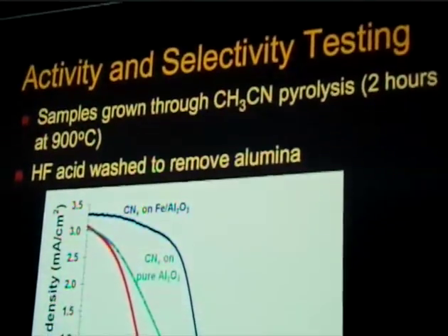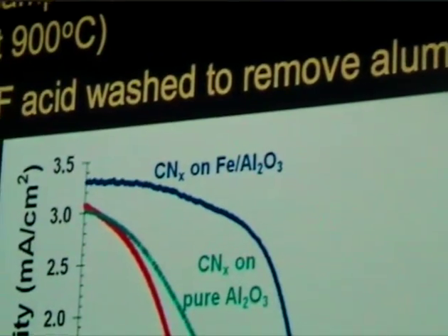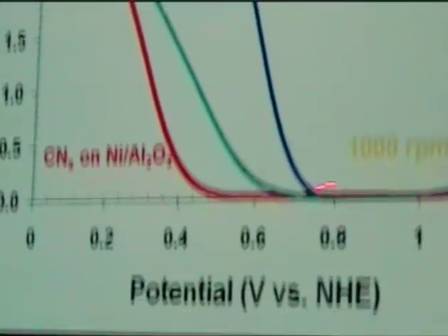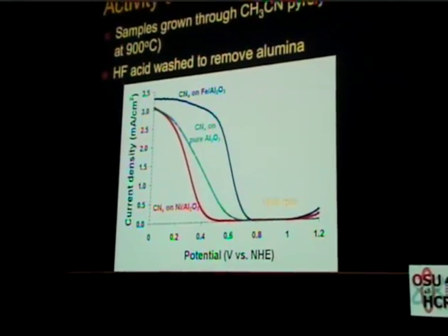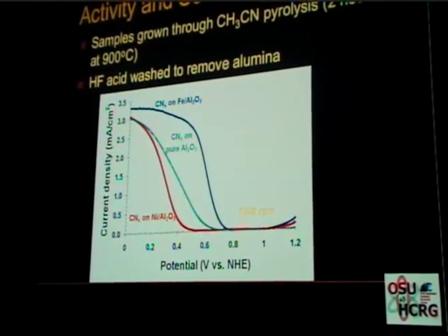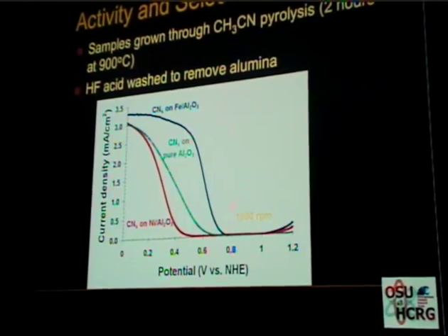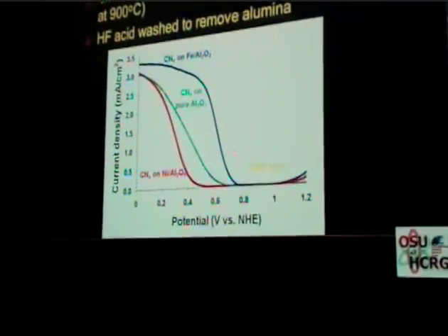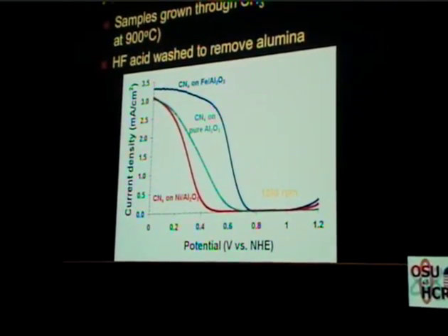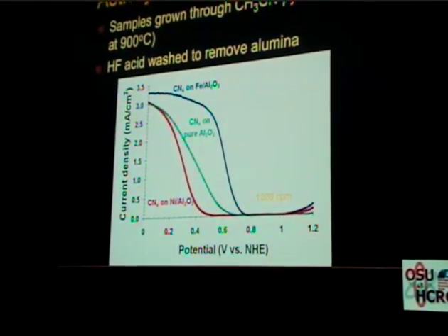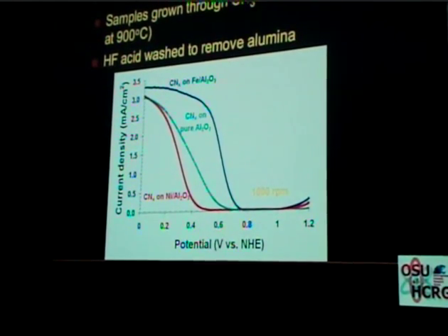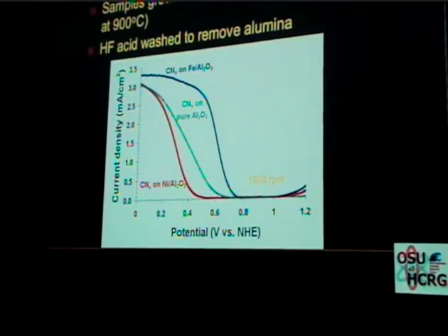Looking at the activity performance of some of these materials, as you can see, these are done using 1000 RPM, so we're really looking at the baseline separation. The particles which are grown on iron-containing alumina take off much faster, so they have higher activity, and then come the ones which are grown on alumina, and the worst performance is given by the particles which are grown on nickel-containing alumina. These are after hydrofluoric acid washing.